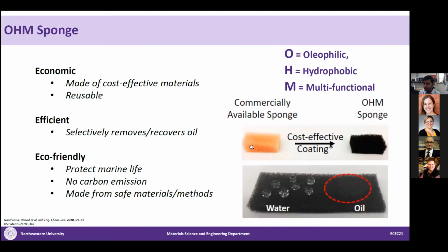By coating a commercially available sponge using multifunctional nanostructures, we have developed OHM Sponge, which is oleophilic, that means it loves oil, and hydrophobic, which means it resists water. So when you introduce this in an oil-water mixture or oil-water interface, it selectively absorbs oil and just repels water. As you can see in the figure below, water droplets do not enter the sponge, they just form balls here, and in the next one, there is oil which is completely absorbed in the sponge. So when you introduce this OHM Sponge to any oil spill, it selectively absorbs oil, and then this oil can be recovered by squeezing it, and the sponge can be reused many number of times.